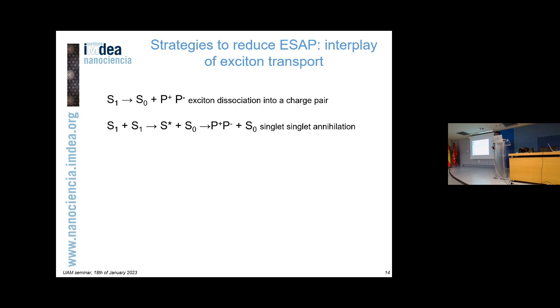On top of that, when you pump high in energy, you also have a large probability of collision, what we call singlet-singlet annihilation, and the formation of upper lying energy levels, which can dissociate with much higher probability. So putting an excess of energy can essentially increase the rate of this process.